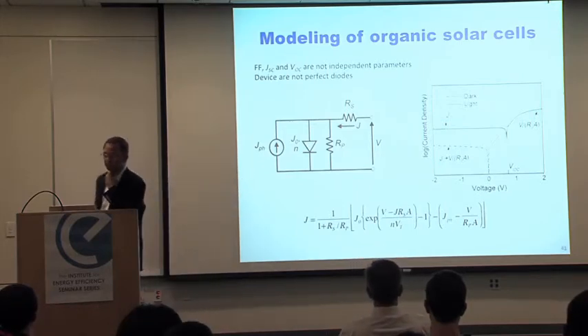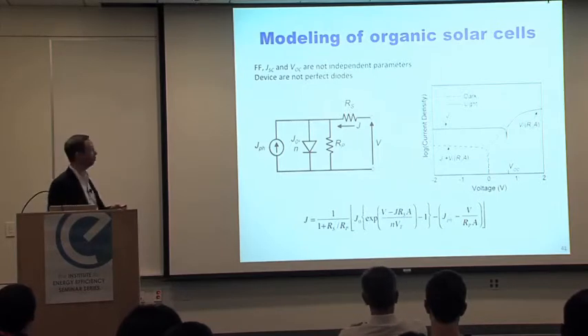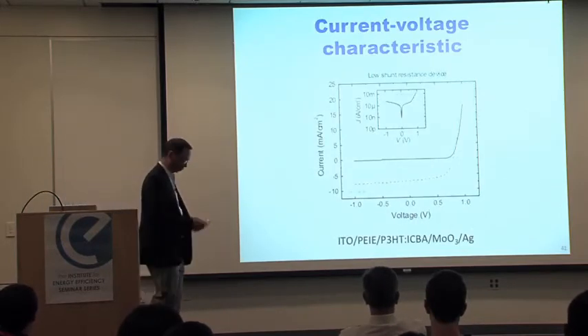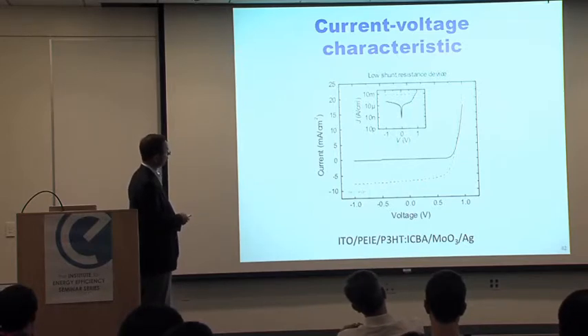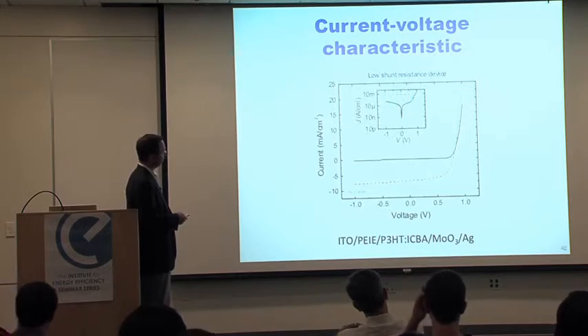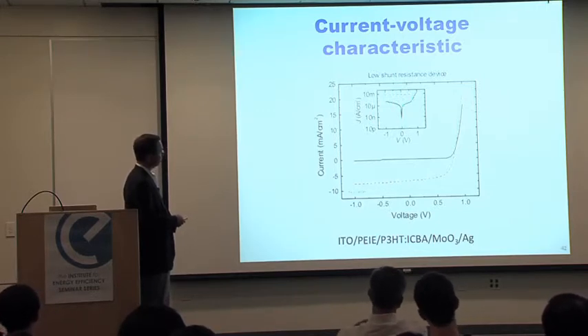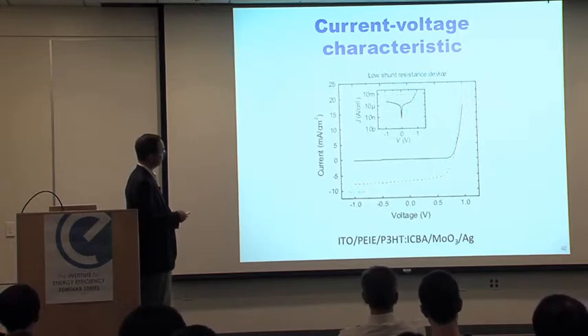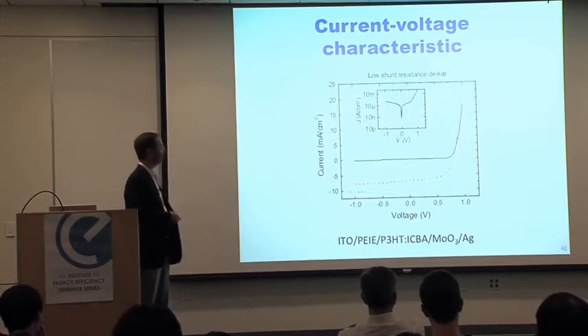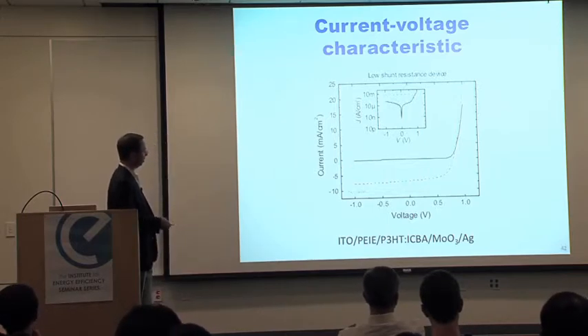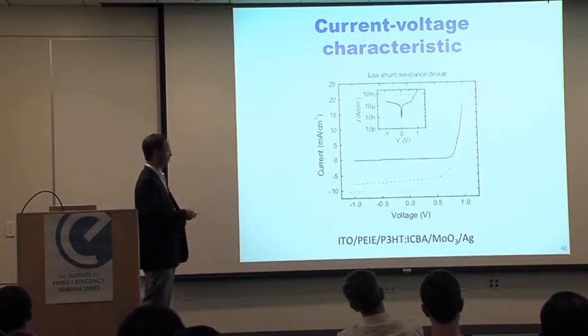And we felt good about this, but as soon as we looked at the current voltage characteristics of bulk heterojunction solar cells, you can see from the dark current here in a semi-logarithmic representation that the shape was slightly different from what you expect from an ideal diode. So here, these are the conventional linear plots. So you see the current voltage characteristic in the dark. You see the current voltage characteristic under illumination. And the inset is just a semi-logarithmic plot here.